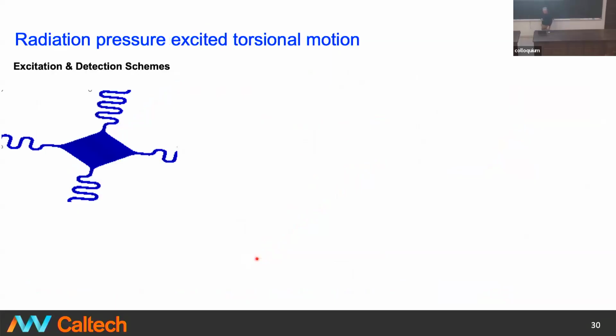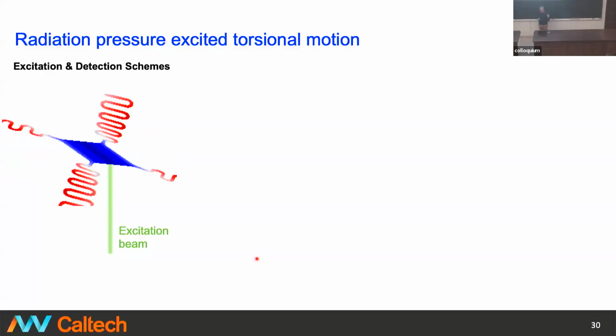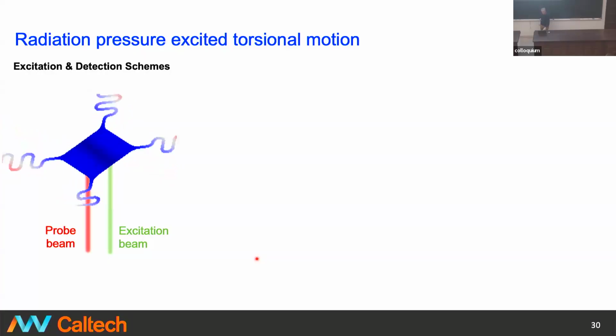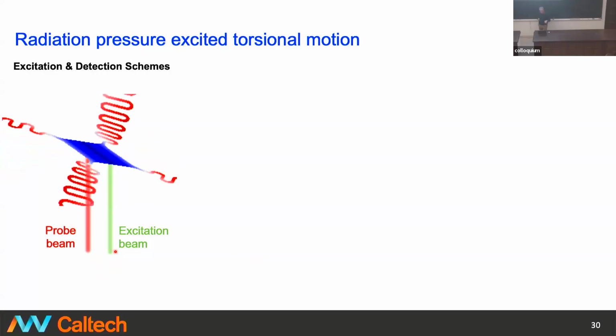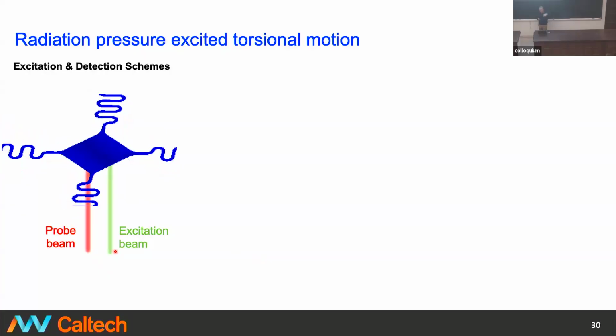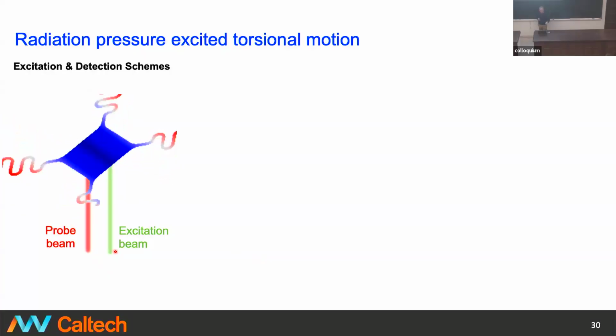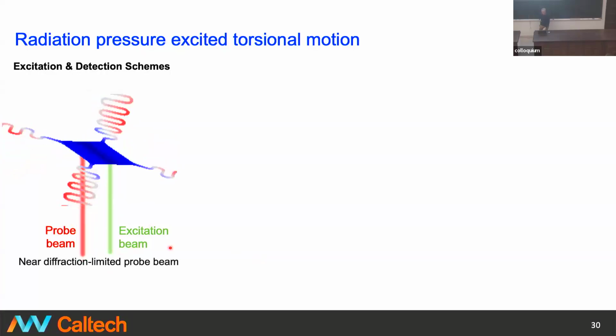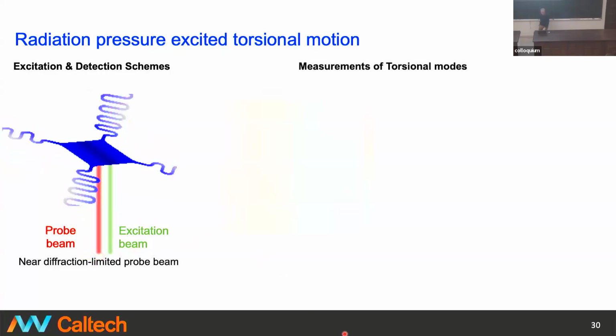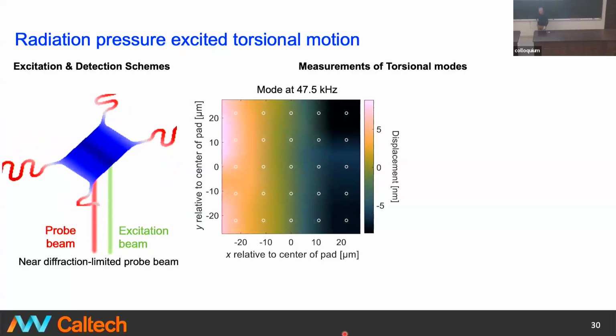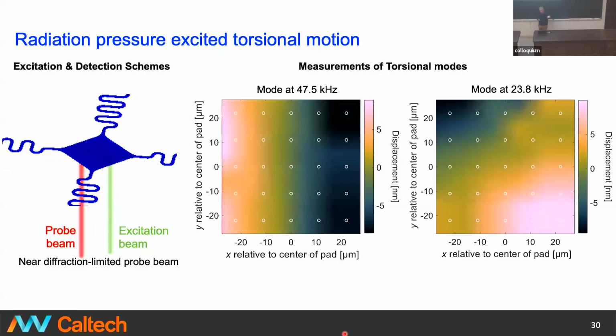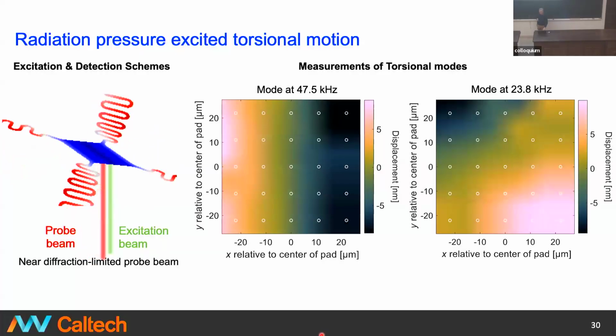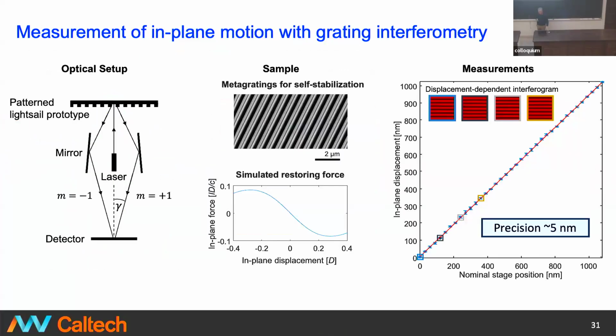So we also were able to look at the torsional modes. In the case of a torsional mode, we use one of these small diffraction limited spots as an excitation beam, and then another one as a probe beam. This is the common path interferometer probe that has a spot size of a micron or so. Now, if I probe off the centroid, or pump off the centroid of this structure, I'm going to induce torsional oscillations. That can give rise to higher order modes that I can see, and I can map out these higher order modes of this oscillation. So I'm now learning something about the properties of this membrane itself and all of its body dynamics.